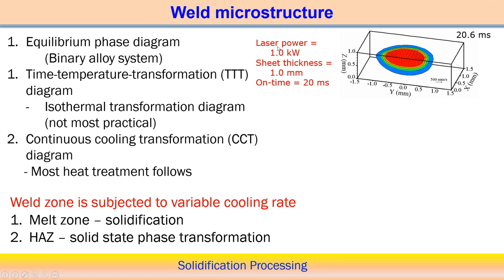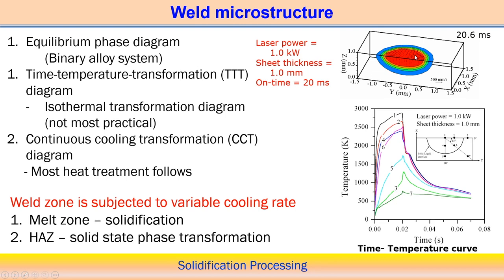Now, since it is subject to variable cooling rates, just as an example, this particular simulation is performed for the laser welding process. Here the laser power is 1 kilowatt, the sheet thickness is only 1 millimeter, and the laser on time is 20 milliseconds. So, after 20 milliseconds of heating we allow it to cool, and after 20.6 milliseconds this is the shape of the weld pool. The red zone basically indicates the weld pool shape, and the other colors indicate the heat affected zone. So this kind of information is useful, and we can see the time temperature history also.